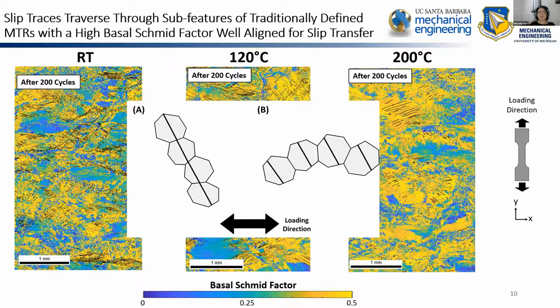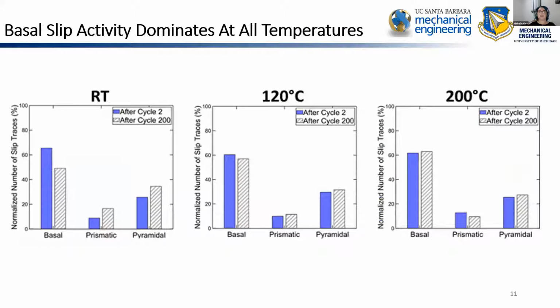And so the question is, we know that all of the slip is existing within these basal regions, but what type of slip activity do we actually have? What we're able to do is take the actual angle of the slip traces and compare it with the projected angle from our orientation map that we would expect to get, and then identify what type of slip traces we have. And for every single case, we have basal slip that is dominating the slip activity, with very little prismatic slip and a little bit of pyramidal. And so for each one of these cases, since they're happening in regions with high basal Schmid factors, and it's basal slip activity, that is what's driving this load shedding phenomenon. That is what's driving these long-range slip features. And that's incredibly important whenever we're considering how things are acting cooperatively and what's important relative to load shedding and dwell fatigue phenomena.